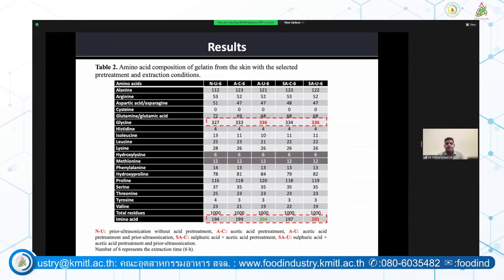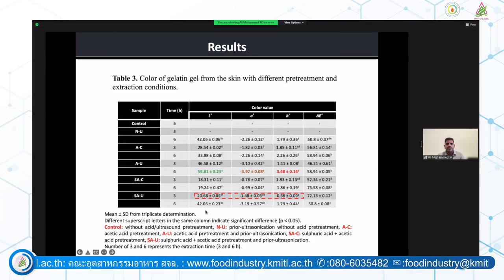This amino acid content in turn will help in the formation of cross-linkages when we prepare food products such as jellies. And we saw the color pattern of these gels when we cast them, and we could see the transparency and lightness: the acetic acid extracted gels were very light and very clear, while the sulfuric acid extracted gels were mildly light and semi-transparent. It could be due to the co-extraction or the breakdown of larger molecular protein gelatin into smaller fractions. So this could be the reason why the lightness has reduced in sulfuric acid treated samples.